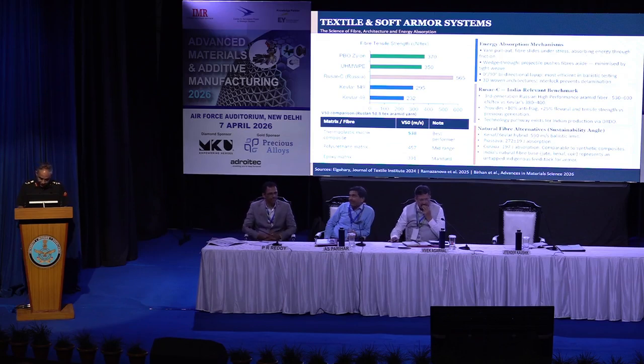The matrix material is a procurement decision, not a science decision. Same fiber, same weight. Thermoplastic matrix gives 538 meters per second V50, whereas epoxy gives 391, a 38% improvement, by changing only the binder. That is the specification lever available today. So that means we have to be very aware of that. With the same material, if the specifications and structural changes are made, the improvement in the outcome can be achieved.